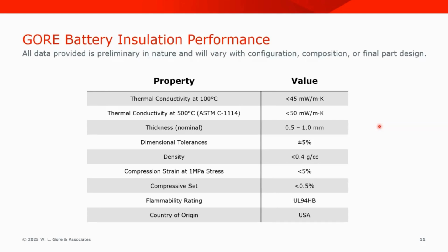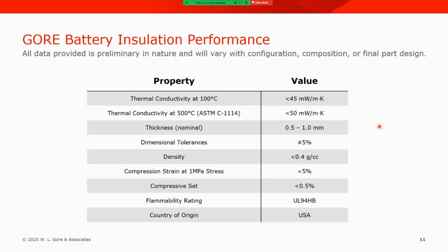As we mentioned, we can produce this in tape form nominally at 1 millimeter, but we can have discussions about producing in thicknesses less than a millimeter. Dimensional tolerances are very tight at plus or minus 5%. Very low density material, less than about 0.4 grams per cc. And as I mentioned, the differentiation between GORE battery insulation and other materials is in its performance under pressure, under compressive stress. So the compressive strain at 1 megapascal of stress is less than 5%. And we're going to dive into this in the subsequent slides.